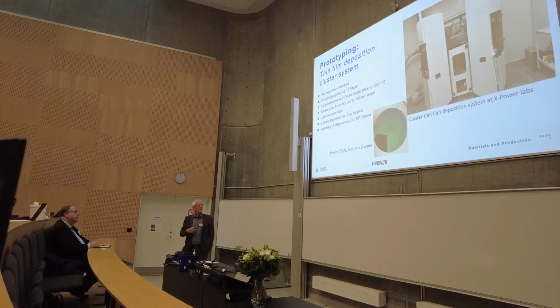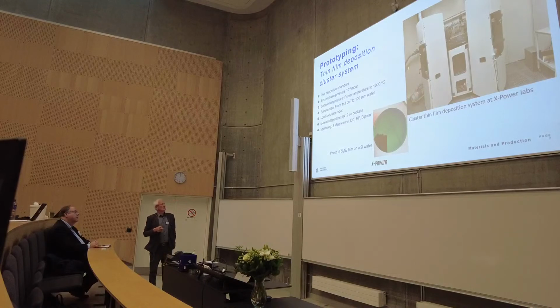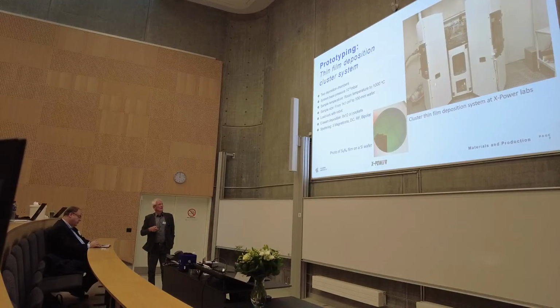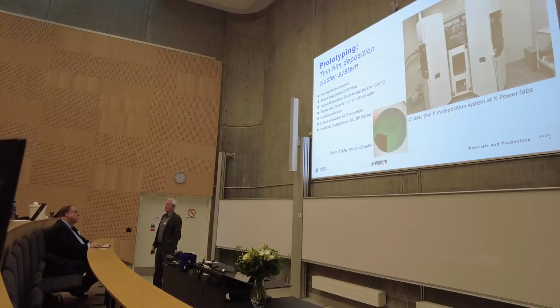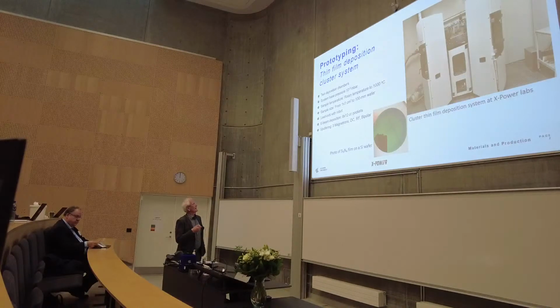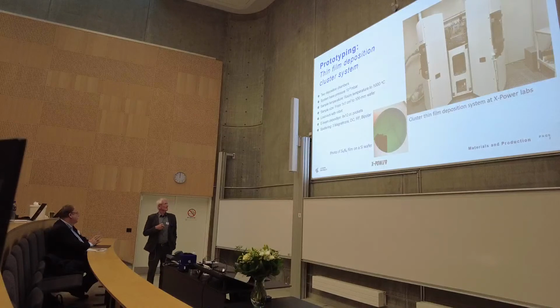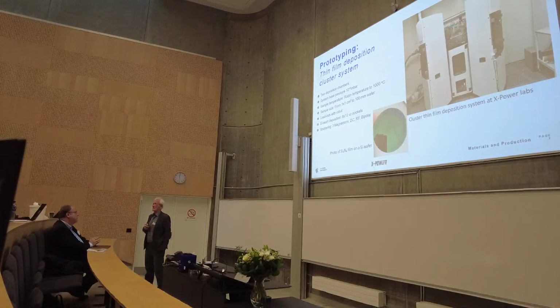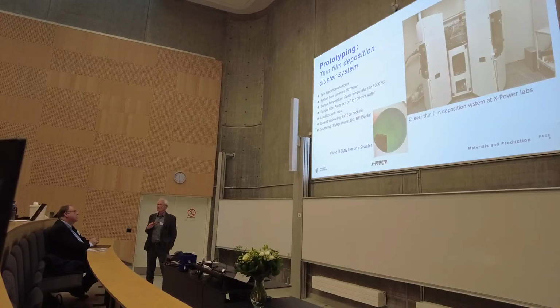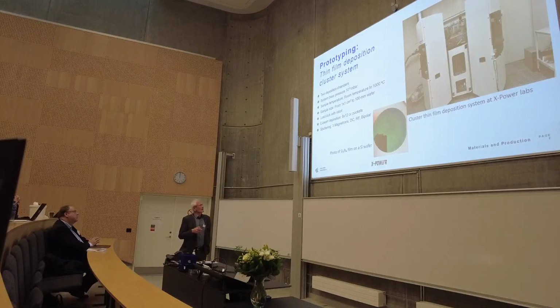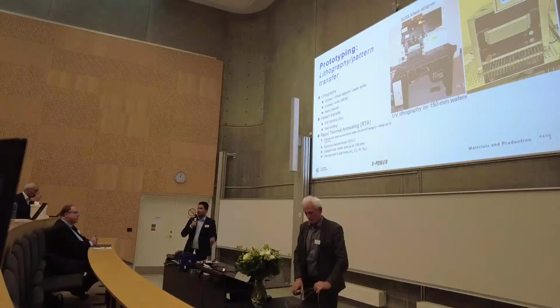Then we have an extremely nice cluster thin film deposition system here. It consists of two chambers, one for electron beam and one for sputtering. Nobody here knows if I was pointing at the right ones. I don't remember which is which either. They have a nice base pressure, 10 to the minus 9 millibar, and you can take the sample up to 1,000 degrees in them. These are quite unique things for a deposition system like this. They are coupled with a robot in the middle, so we're actually looking at the back side of it. From the front side, you just see